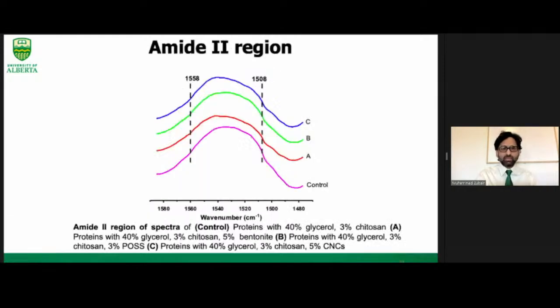Furthermore, the amide 2 region was expanded to see the changes in it. In the amide 2 region of the nanoparticle-added proteins, we can see that the intensity in this region was increased. So that shows that the NH bond in this region has a maximum number of hydrogen bonds as compared to the pure proteins.